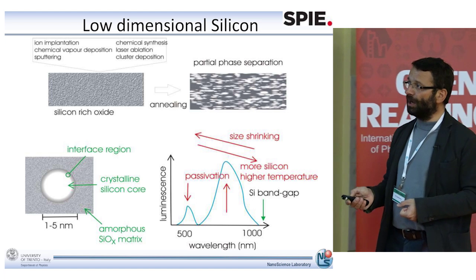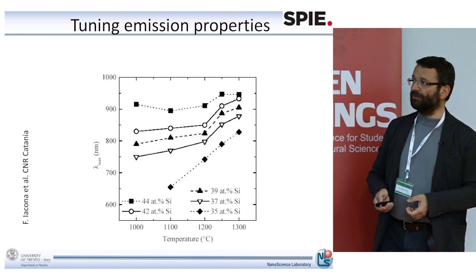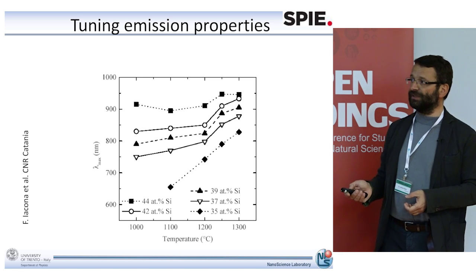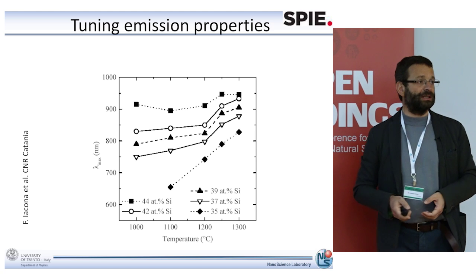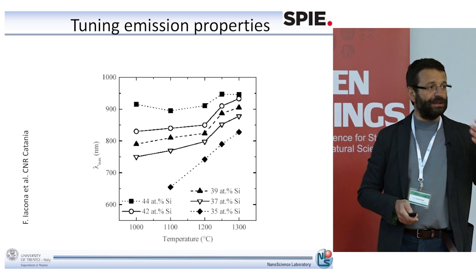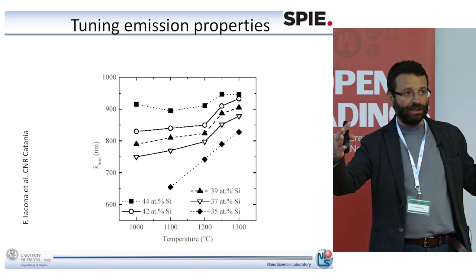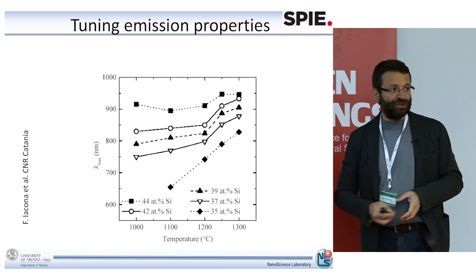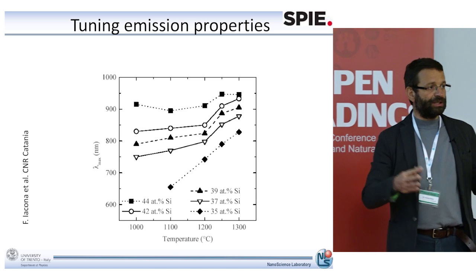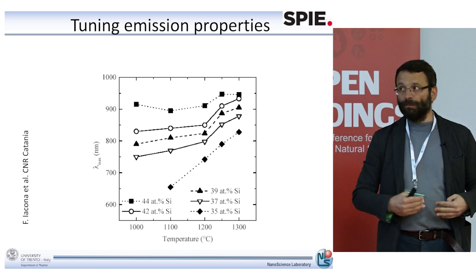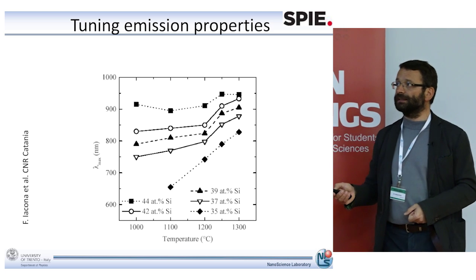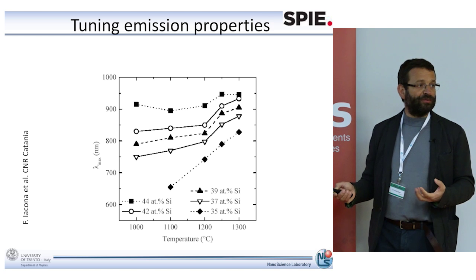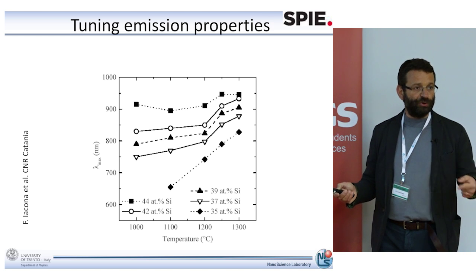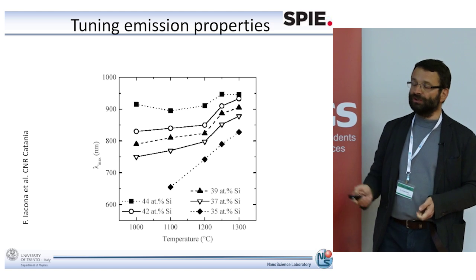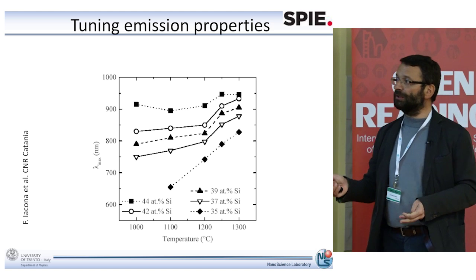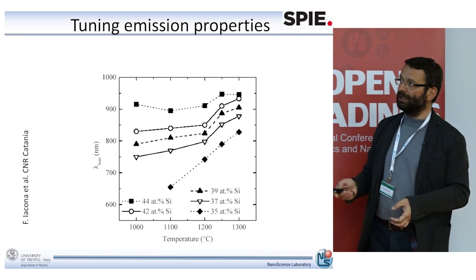So here is an example of the emission wavelength of several silicon nanocrystals as a function of the annealing temperature for different silicon content in the film. You increase the silicon content, and so you grow larger nanocrystals. You increase the annealing temperature, and so you grow larger nanocrystals. Larger nanocrystals, less quantum confinement, more red shift in the luminescence. And so you see that the peak of the emission, here in wavelength, inversely proportional to the energy, shifts to the red, caused by the fact that the nanocrystals grow in size.